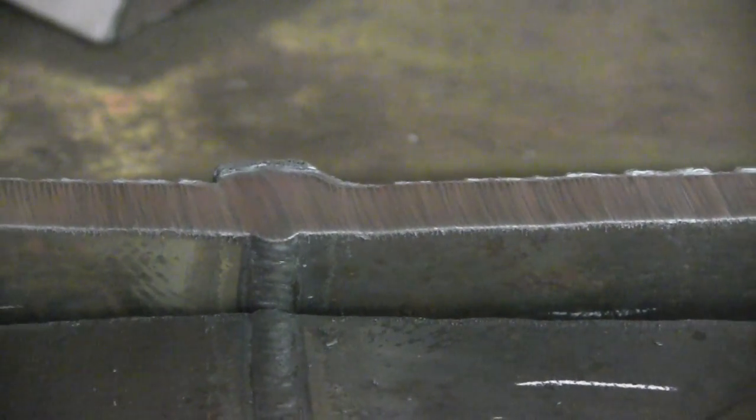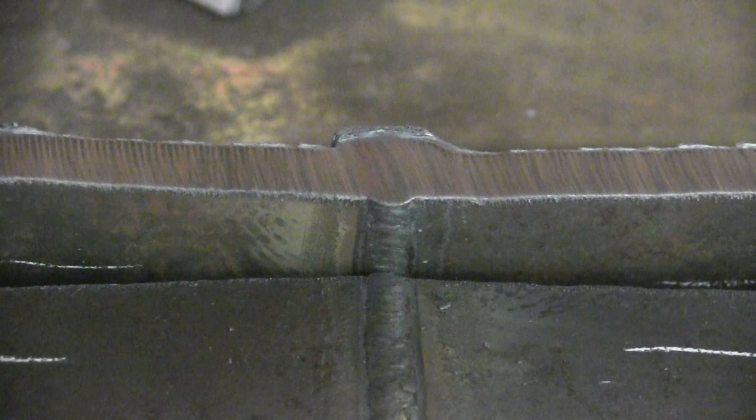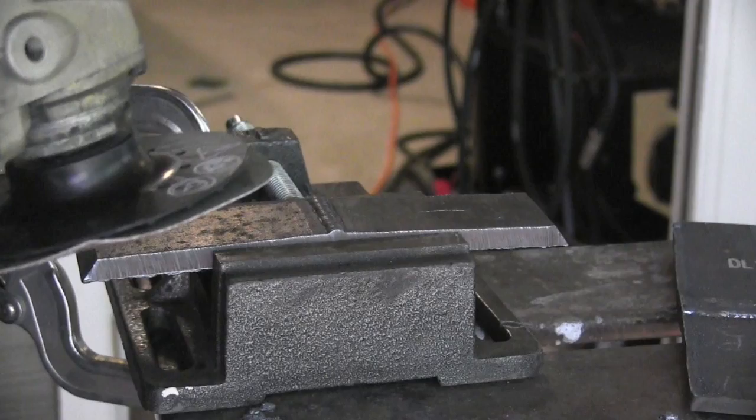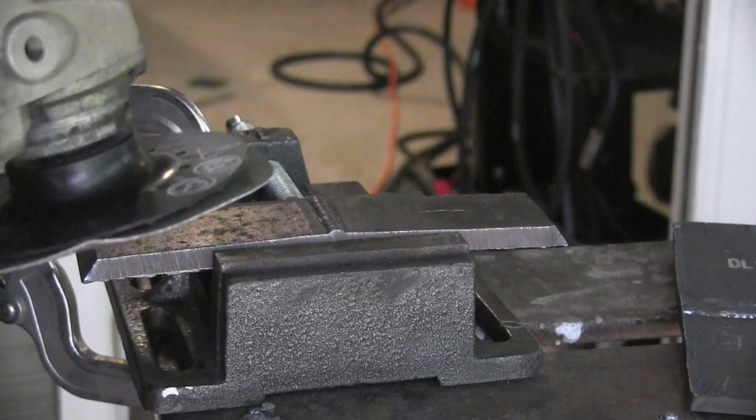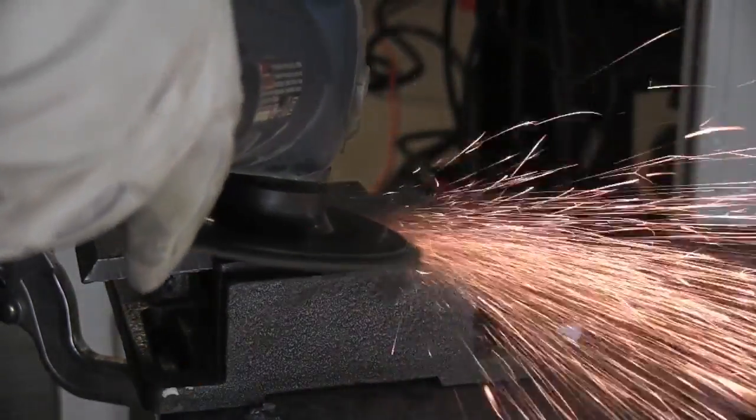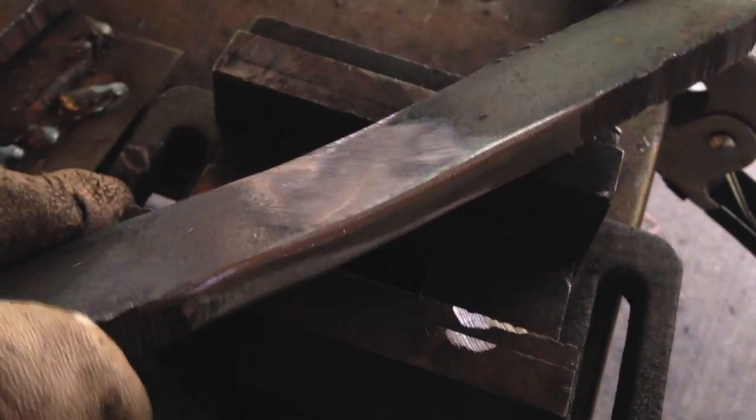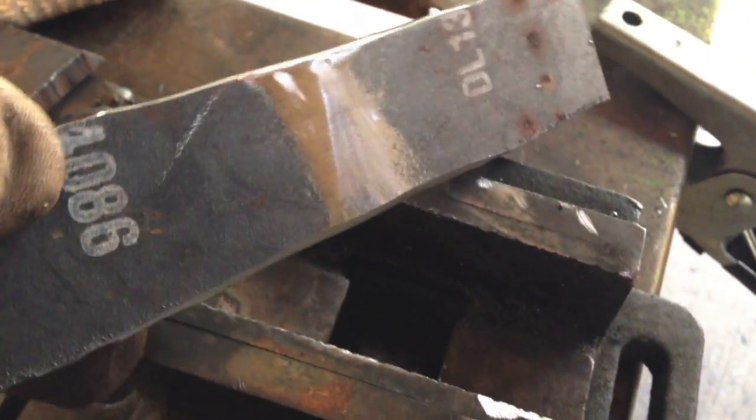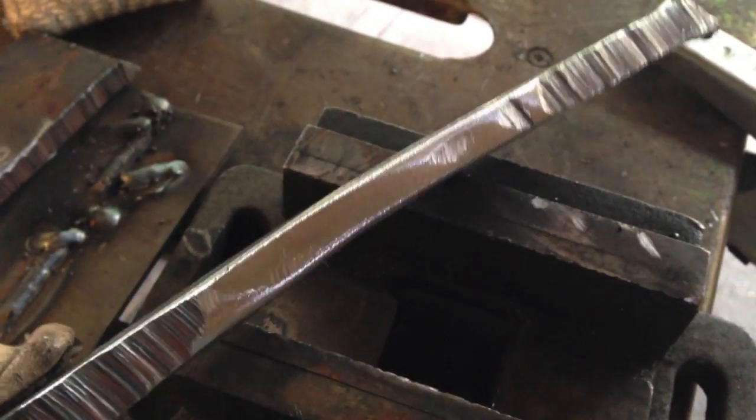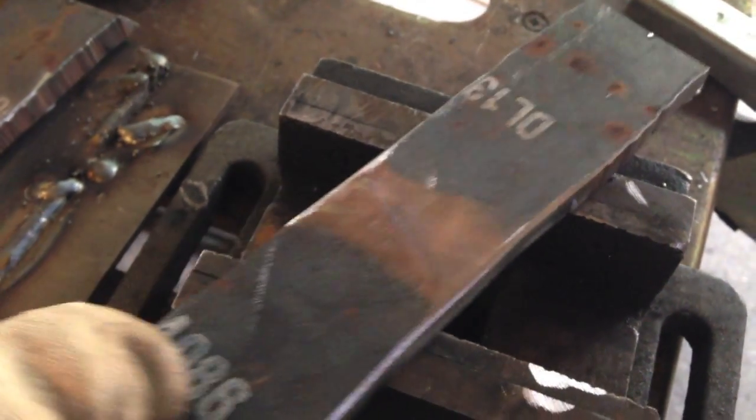Now we let them cool and grind the straps and we'll be ready to bend them here shortly. I put the strap in this little drill press vise, easy way to hold them while I grind on them. And you want to radius the corners and you want a nice smooth surface and you don't want scratches running sideways.